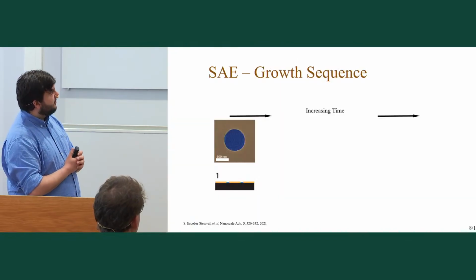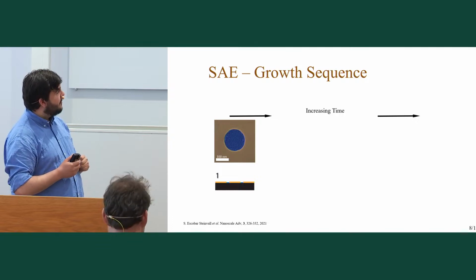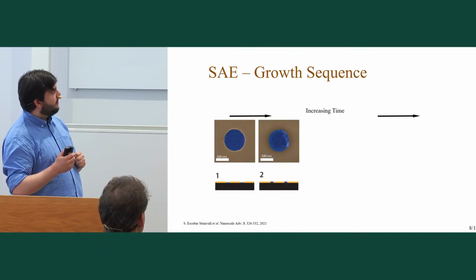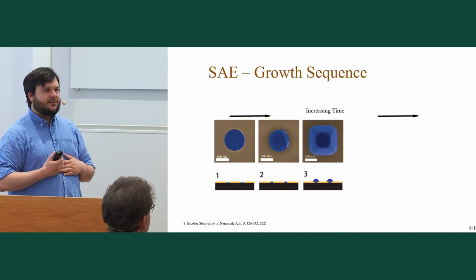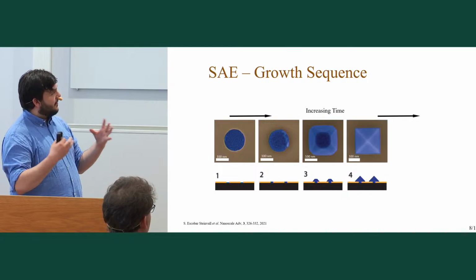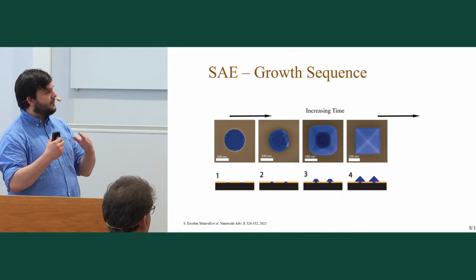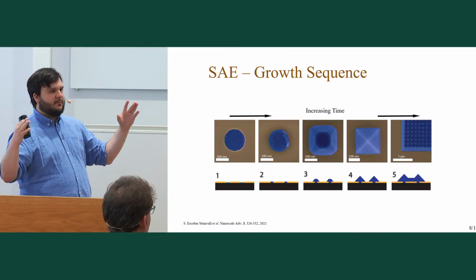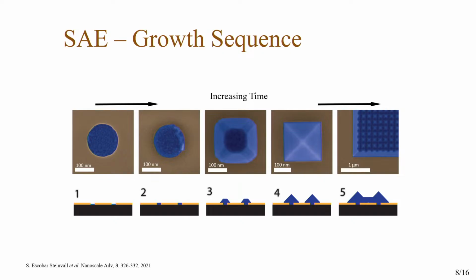So the way this works with zinc phosphide is we have this hole where we're trying to grow selectively. We deposit zinc and phosphorus, and it starts to grow in the hole. And then when we thought we were going to start growing a nanowire, it started growing like a pyramid. And with enough time, it grows into a full pyramid. And if you have them next to each other, you get these films with a pyramidal texture. Now, if you look at a silicon solar cell with the highest efficiency, they actually try to achieve this texture by introducing extra etching and processing steps. So they do extra work to try and get this texture that we're getting for free. So I was trying to grow nanowires, but I got this instead. And now we're 7 universities all across Europe trying to develop this further through this EU project.